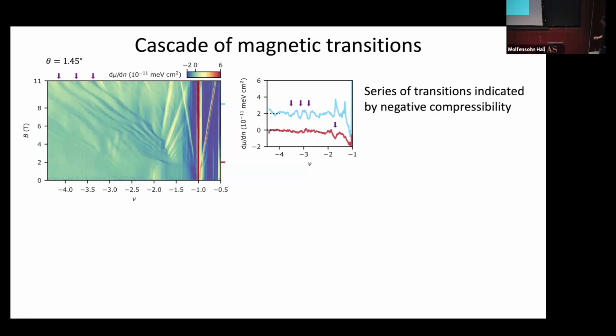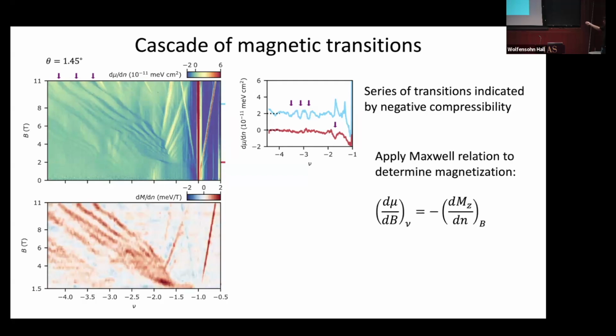And in fact, from our compressibility data, we can integrate to get d mu dB. We take a cut vertically to get d mu dB, and Maxwell relations tell us that that's related to the change in Z magnetization with respect to carrier density in our sample. And so in this way, we can figure out what is the change in magnetization throughout this phase diagram as well. And you can see that these diagonal features here correspond to magnetic transitions. I won't spend the time to go through the details, but this corresponds to filling one Hofstadter subband at a time, basically flipping the spin polarization of subbands in this Hofstadter regime.